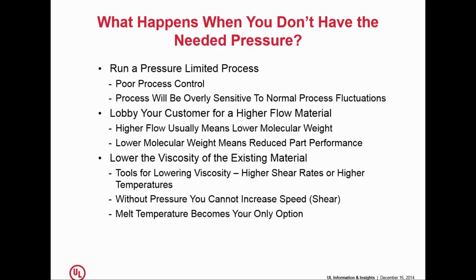The other option you have is to lower the viscosity of the existing material. And we have 2 tools for modifying viscosity in a polymer. One is the temperature of the material, and the other is the shear rate. Well, we've already talked about the fact that shear rate's related to velocity, and if you don't have enough pressure, you can't change velocity. So now you're stuck with one option, and that is to increase the melt temperature until the material starts to flow the way you expect it to flow.